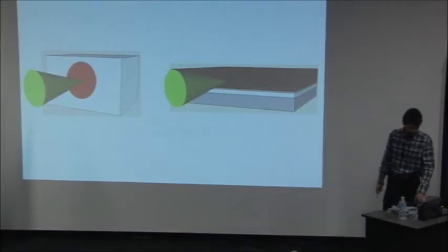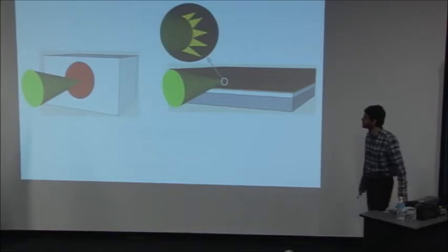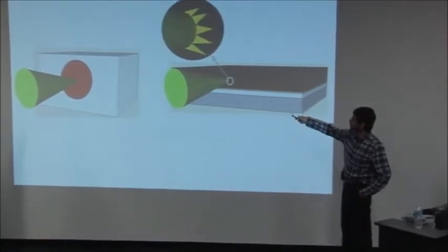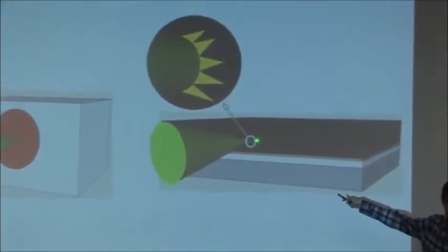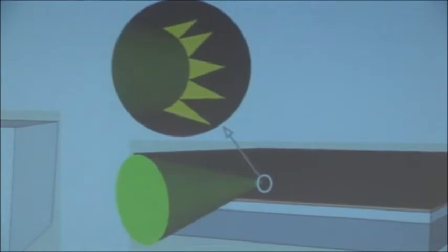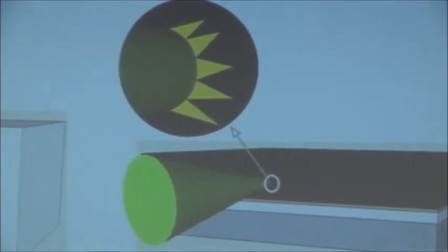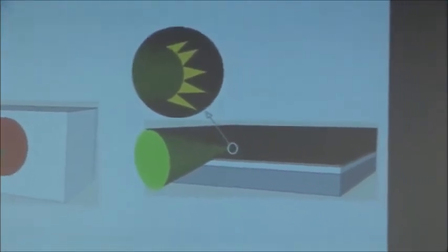So they're good conductors. What we saw when we looked very closely was that, in fact, no, the heat was localized more or less to the spot where the laser is illuminating the sample. That was, again, quite surprising. How can that be? Isn't it supposed to spread? But this wasn't happening.